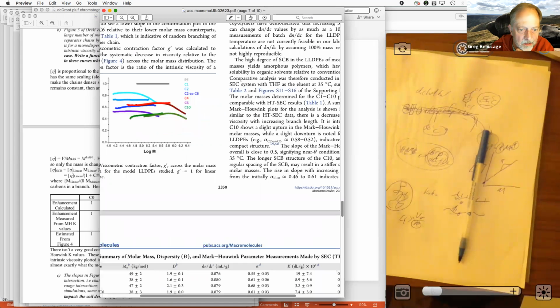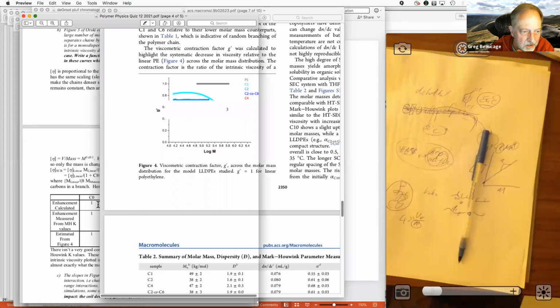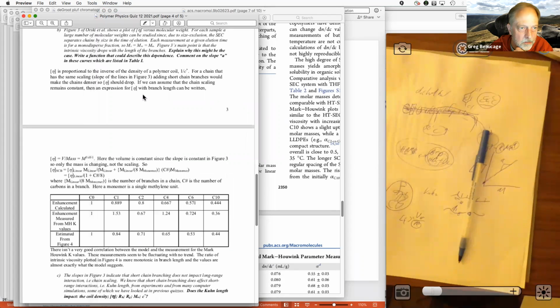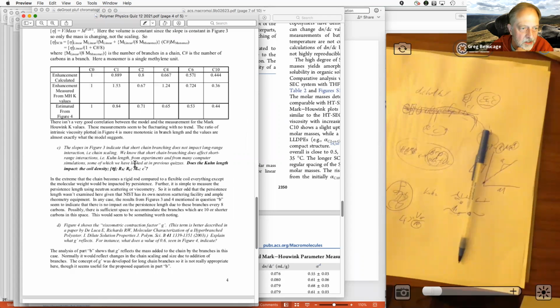Right, so you can get a pretty good idea what the values are here. And they're almost exactly the same as the predicted, this kind of simple equation. So it's 0.88, 0.84, 0.8, 0.7, 0.66, 0.65. They're almost the same number. Some are exactly the same. So I mean, that works pretty well as a model for what's going on here. They didn't do that in the paper. They probably should have, but anyway, so that's part B.